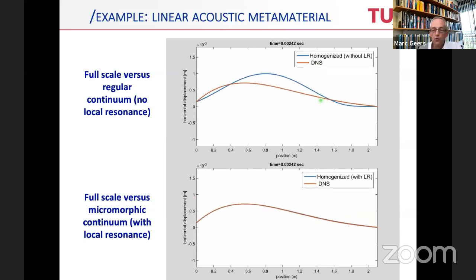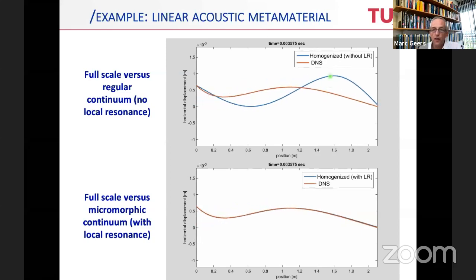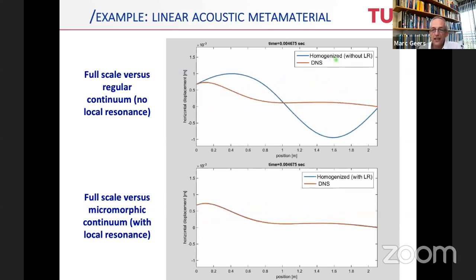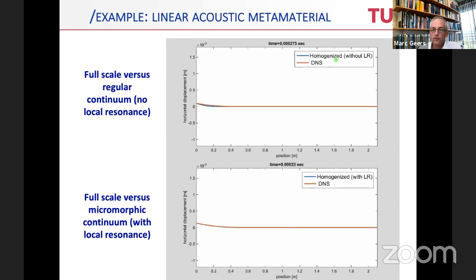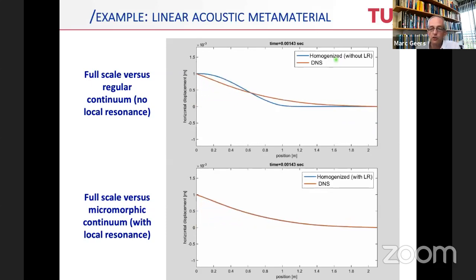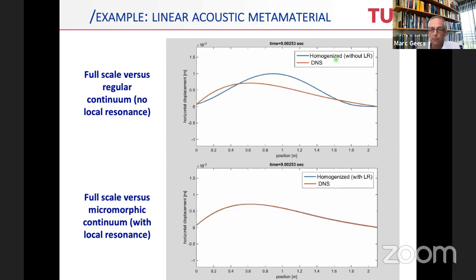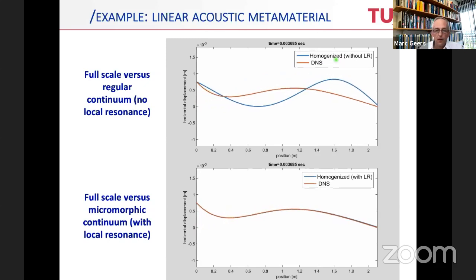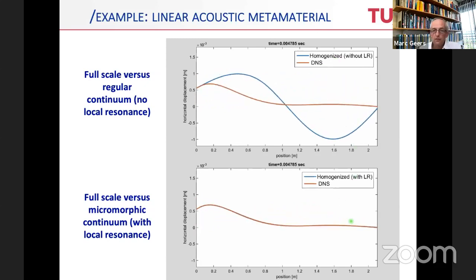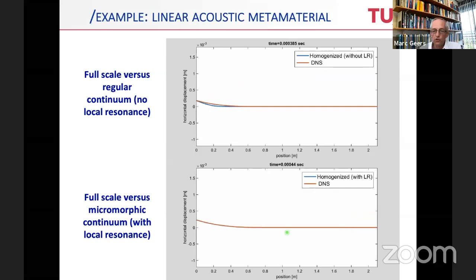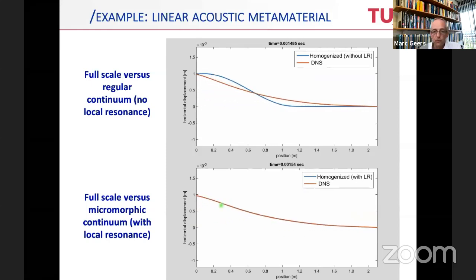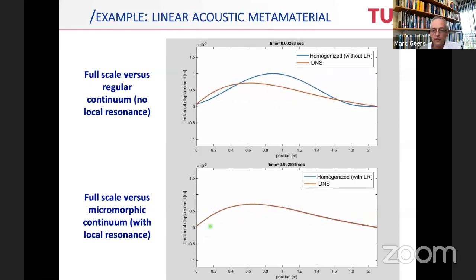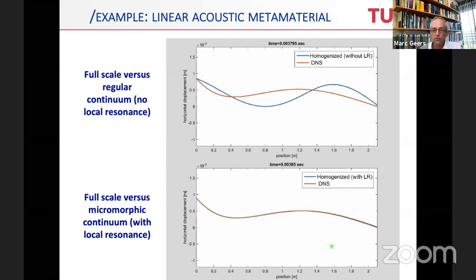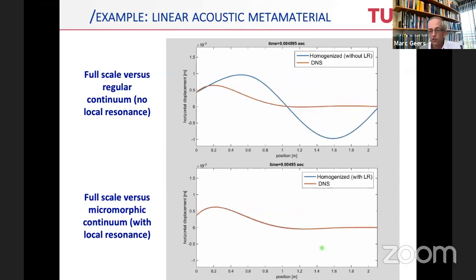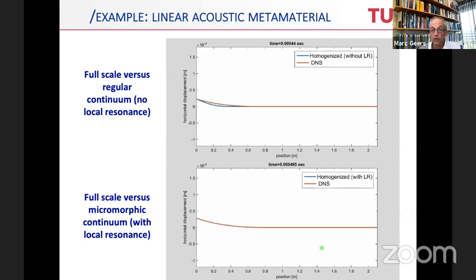The DNS solution, that's the expected solution. The blue solution, that's the classical homogenization scheme. And as you can clearly see, the classical homogenization scheme cannot pick up this phenomenon. On the bottom, you actually see the homogenized scheme that includes resonance. And there, fortunately, the homogenized result falls on top of the DNS results, which again shows that the model is doing a very good job.